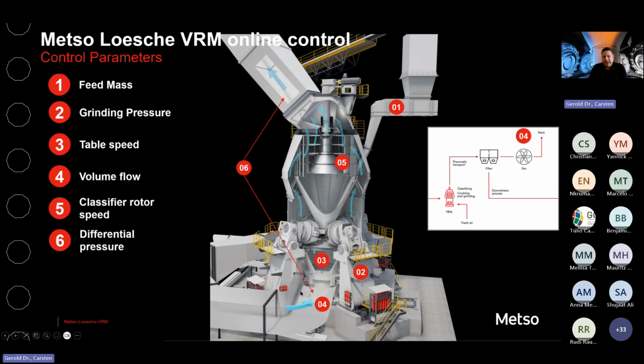What we see as a really big advantage is the differential pressure that we measure. When commissioning the plant, we measure the differential pressure, which is nothing else than a signal for the internal circulation we have in the mill. And you can identify when this is at an optimum point. Let's assume your feed is getting softer. What would happen? It would grind faster, so it would leave the circuit faster. At the same time, you see that the pressure drop is reducing, which means the mill has capacity left. Then you can automate your feed to stabilize that pressure drop, which means nothing else than feeding more material to the mill, and therefore utilizing the mill to the maximum.